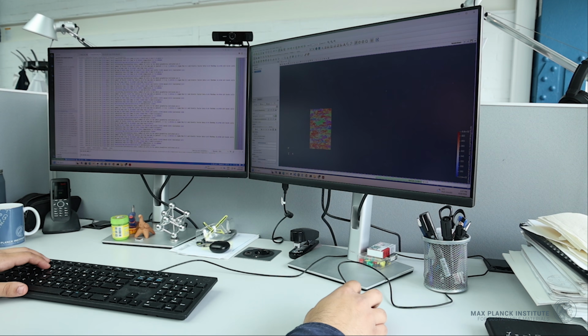On the mechanics front, we are using our own in-house developed code, DAMASK, where we are simulating the deformation processes and how each grain deforms inside the metal and how texture is formed, using full-field crystal plasticity simulations. Then, after that, we couple it with the recrystallization software we are developing here to model how recrystallization textures arise from the DAMASK input.